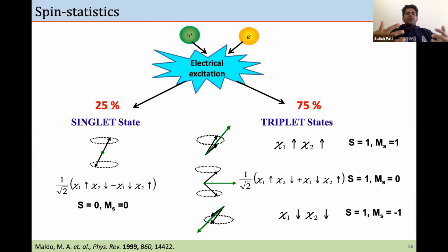What essentially happens here is that you generate 25% singlet state, where total spin is 0 with 0 angular momentum, whereas you also produce 75% triplet. So this is the mathematical ratio, where you produce very few singlets and a very large number of triplets. It's a 1:3 ratio. And as I talked about in the beginning with the Jablonski diagram, triplets are spin forbidden transitions. Just a simple selection rule: the triplets are not that emissive. It's a dark state. What matters for an LED is the singlet state, which is a bright state.